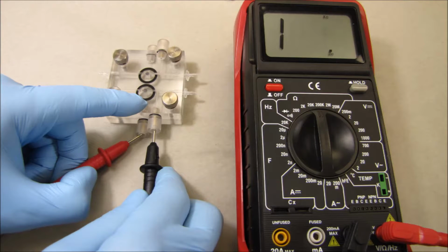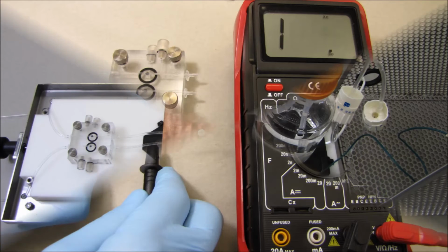Adjust the multimeter setting to 200K ohms, then measure the resistance across two electrodes on the same channel. The value should be below 100,000 ohms, although the ideal is below 20,000 ohms. Values out of range indicate air bubbles in the electrode capillaries. If air in the electrode capillary is suspected, the electrode should be removed, the electrode capillary flushed, and the electrode reinstalled as previously described. Resistance should be brought to acceptable levels before proceeding.